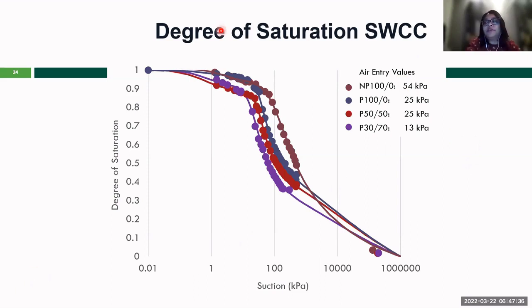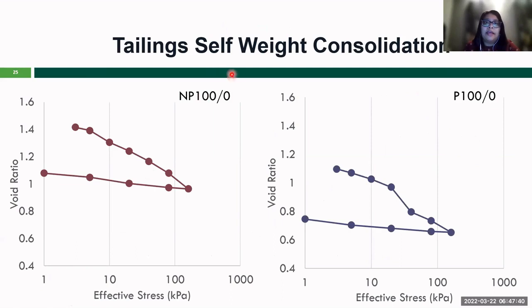So the last figure on these geotechnical tests is the self-weight consolidation that we are going to talk about here. We have only looked into the non-polymer samples, 100% tailing samples, and the polymer 100% tailing samples. The shapes are different. The non-linear shape was observed for the polymer treated sample. And this type of shape is common from the literature for different polymer types, for the concentration of the polymer and testing conditions. So both shapes are common for polymer treated samples, but for our case, we have only seen the non-linear behavior for the self-weight consolidation test data.